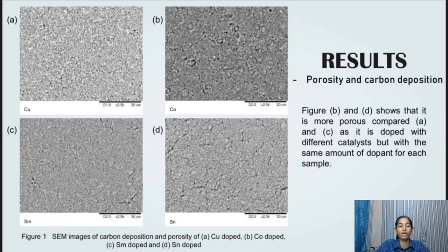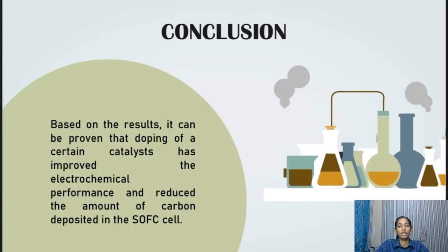So the results obtained are in terms of porosity and carbon deposition. Figure 1 shows the SEM images of carbon deposition and porosity of A, which is copper doped, B, cobalt doped, C, samarium doped, and D, tin doped. It can be observed that figures B and D show that it is more porous compared to figures A and C, as it is doped with different catalysts but with the same amount of dopant for each sample. It can be concluded that doping of a certain catalyst has improved the electrochemical performance and reduced the amount of carbon deposited onto the solid oxide fuel cells.